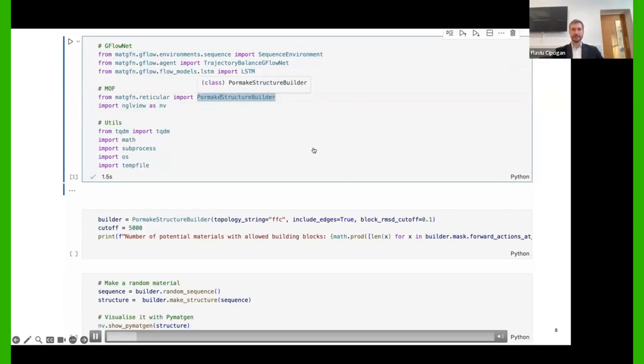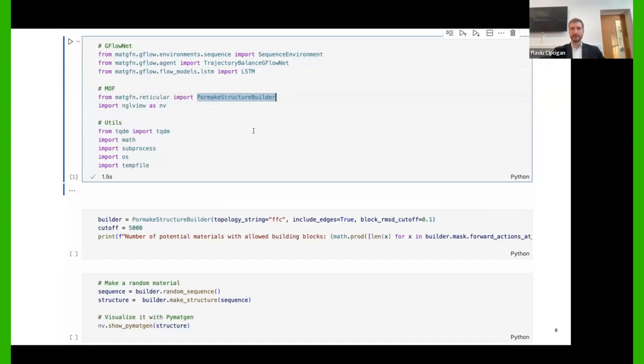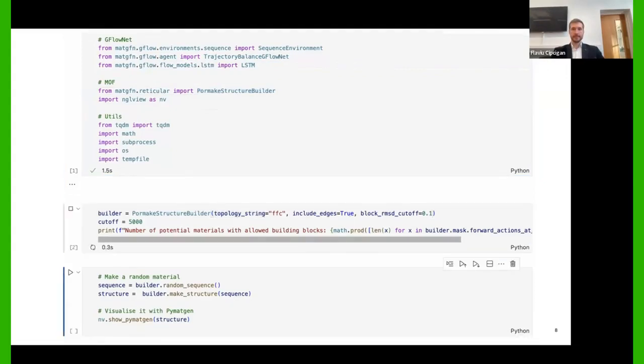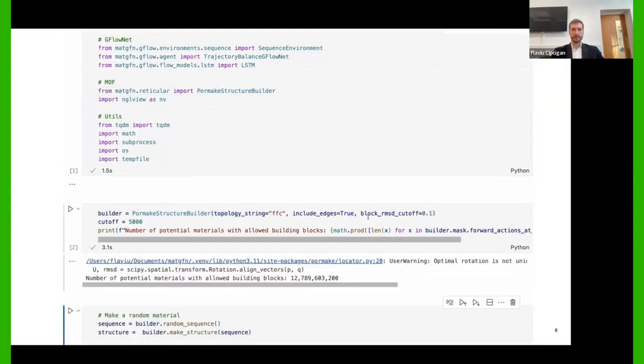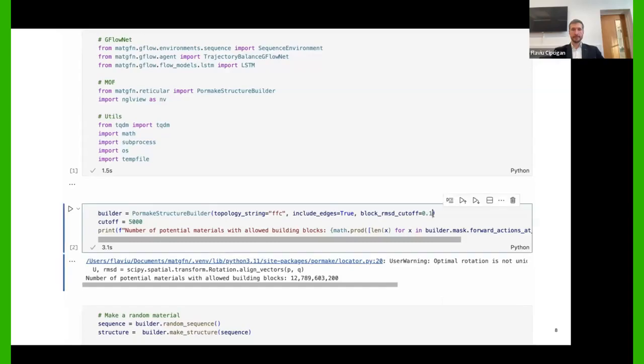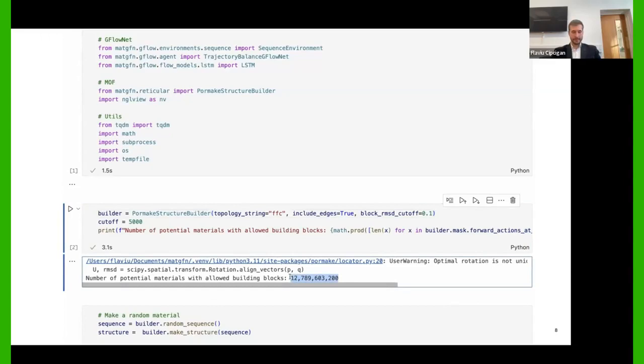We also have the utility class PormakeStructureBuilder that helps generate metal organic frameworks and covalent organic frameworks using the pormake package. We initialize a PormakeStructureBuilder with a certain topology string. Here we do FFC. We include edges and we choose an RMSD cutoff. This means that in each slot of the topology, we will only add blocks which are less than 0.1 angstroms from the size of that block. So we only add compatible blocks in that slot. In this topology, with all of the building blocks in the Pormake library, we have over 12 billion potential candidates. So this is a very large space for the GFlowNet to explore.